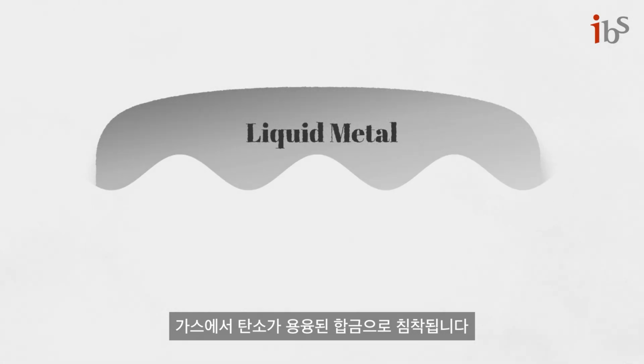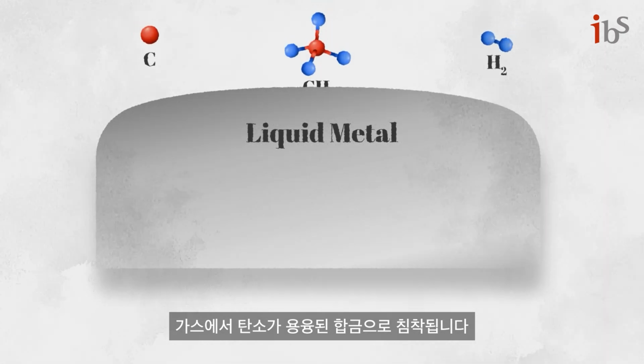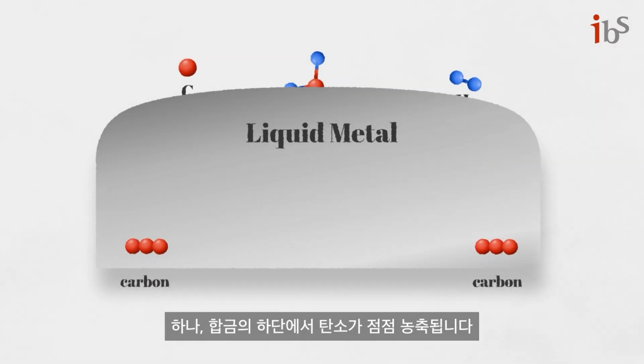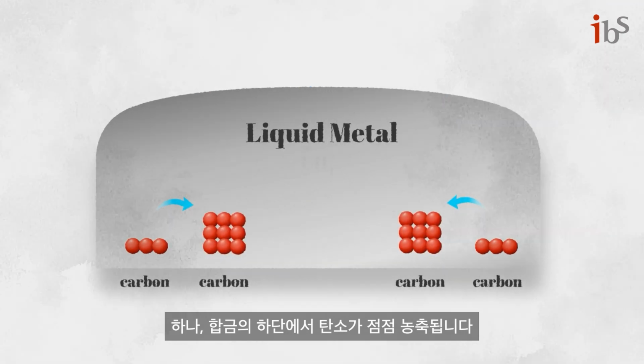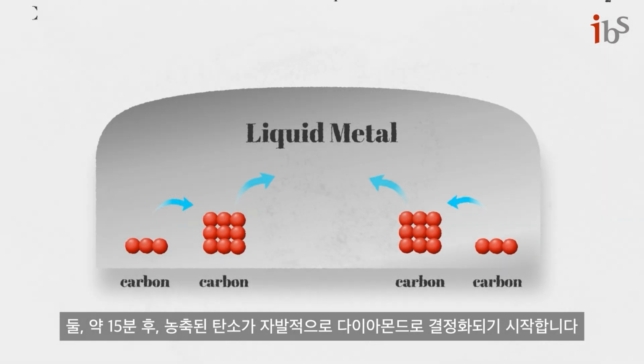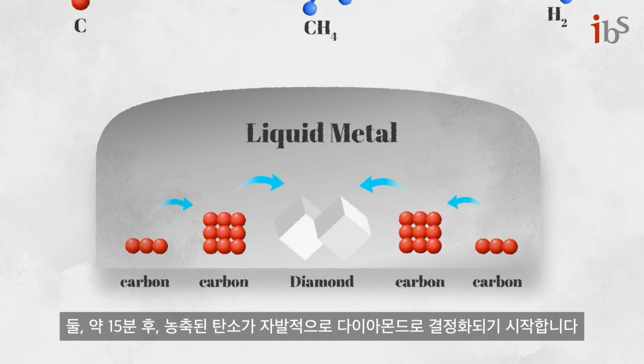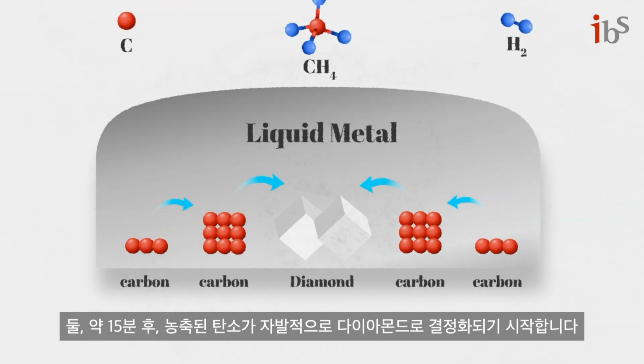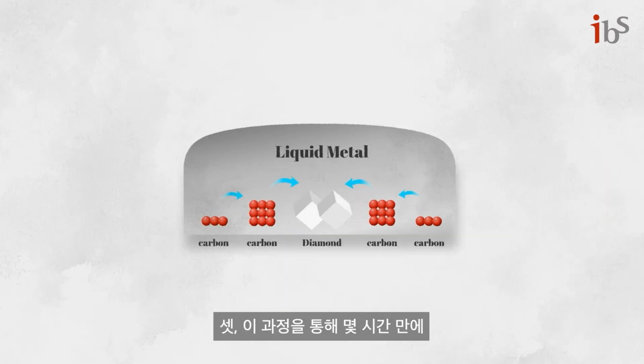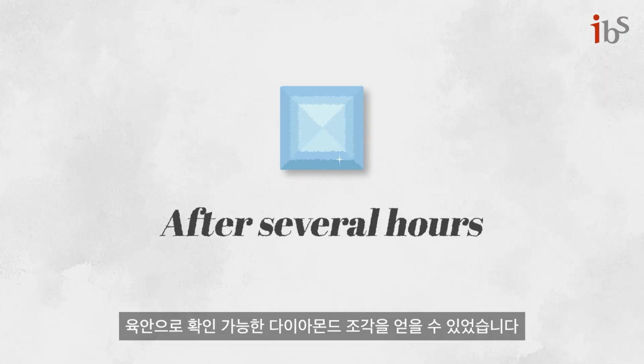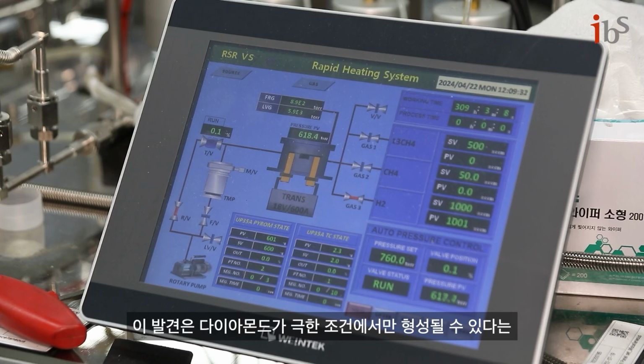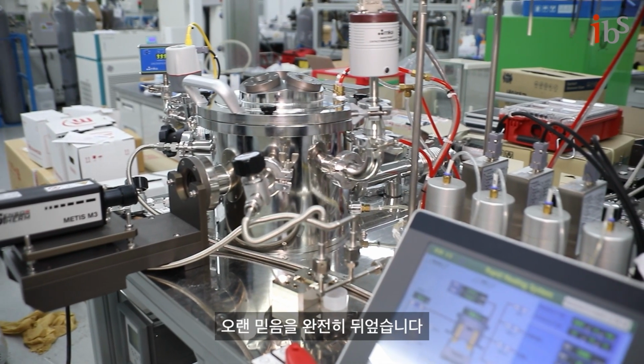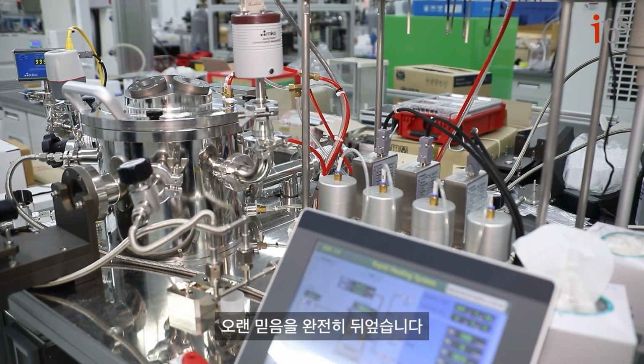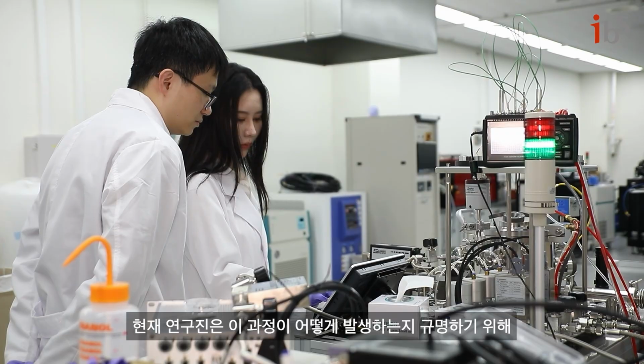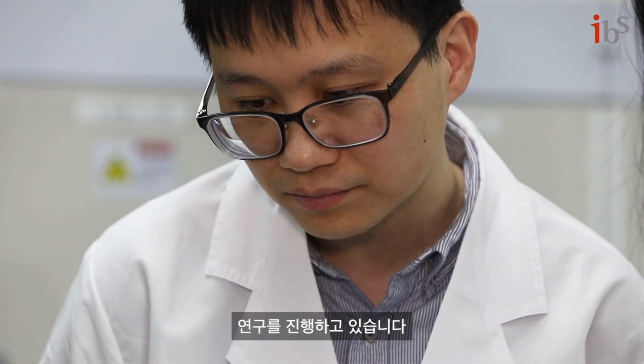The carbon from the gases becomes deposited into the molten alloy. 1. At the bottom of the metal alloy, the carbon becomes increasingly concentrated. 2. After around 15 minutes, the concentrated region of carbon begins to spontaneously crystallize into diamond. 3. It was possible to obtain macroscopic pieces of diamond after only several hours of this process. This discovery completely overhauls the long-standing belief that diamonds can only form under extreme conditions. Currently, the researchers are working to figure out how this process occurs.